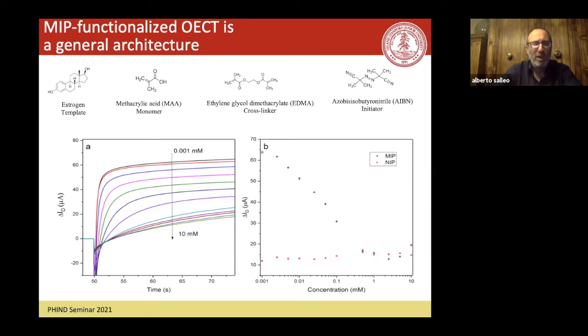So we had summer students. This is done actually by undergrad summer students supervised by the postdoc. So we used estrogen now, built the molecularly imprinted polymer around estrogen, and we were able to sense estrogen as well. So what we like here is that the molecularly imprinted polymer is what makes every sensor different from each other, but the platform is always the same. There's always this electrochemical transistor. So it's very easy now to imagine a completely multiplex sensor where you have 10 or 15 of these little sensors, and they're each functionalized with a different molecularly imprinted polymer, and you can have a complete panel of sensors that will measure a whole range of things in a pretty compact footprint, which is one of the things we're really interested in doing.